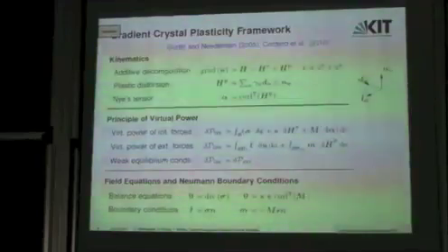And this microscopic information is given in terms of the dislocation density tensor, since this is physically an object which has a physical interpretation, because it represents an effective Burgers vector density of your underlying dislocation density. Of course, you don't resolve the individual dislocation, but you have a kind of effective description of your dislocation network. So you just put in more information and hope that the model gives a better response.